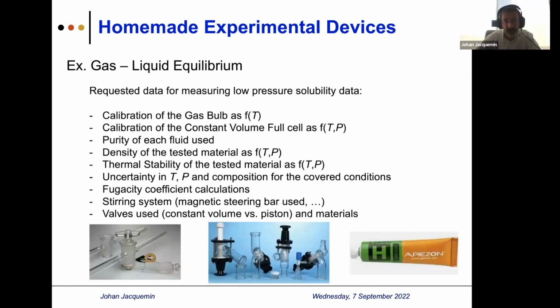Another problem that I would like to share, because I had the chance to build different techniques and different materials, is a very big problem, purely experimental. I use a constant volume valve, a stopcock, I would say, with which you have to count the number of turns. And the piston could be in Teflon, or could be in glass or whatever. And if you're measuring gas solubility, simply avoid Teflon, because you may have problems with the stability of your measurements.